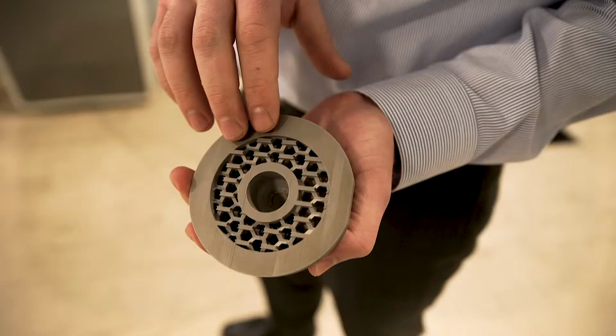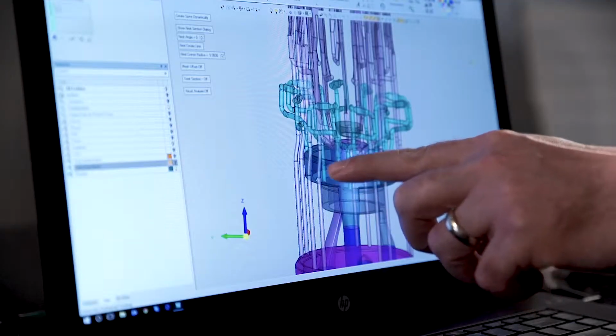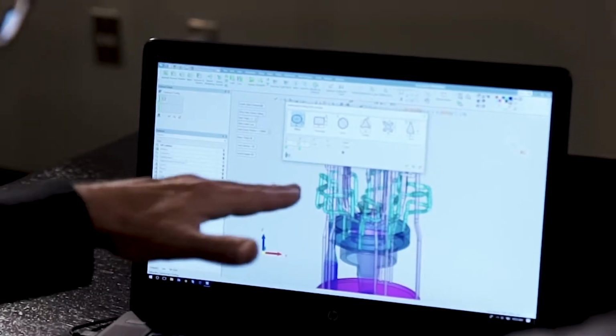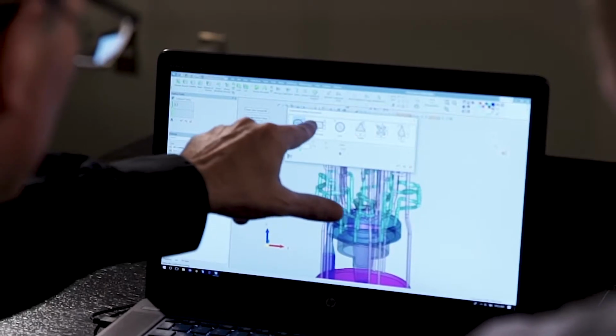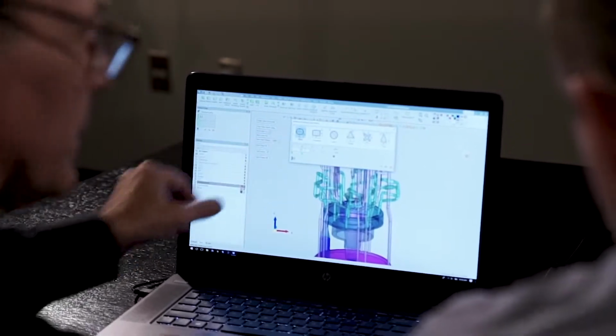Metal printing brings new geometries to conformal cooling that just were really unimaginable 20 years ago. We can get cooling channels to within 2 millimeters of the face of an injection mold tool. There's just really no other way to manufacture those. Conformal cooling integrated into injection mold inserts can reduce cycle times anywhere from 35% all the way up to 70%. And that's a really meaningful improvement when you're looking at a million parts.